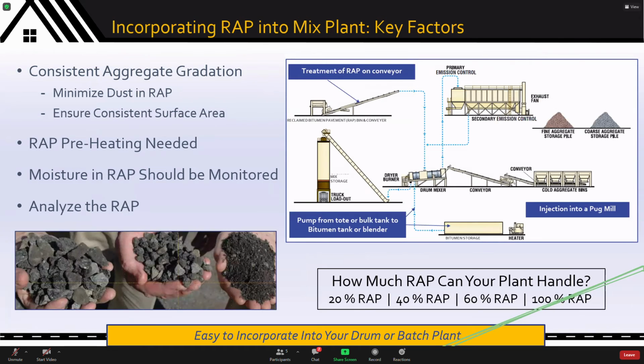So you've done all of this. How do you incorporate high RAP mixes in your plant? Like any input raw material, treat it carefully, measure it well. It is always good practice to try and reduce your RAP piles to different gradation sizes. You can incorporate more and more RAP if you make more and more fractions. This is simply to meet the dry gradation spec requirement that you have to meet. Minimize the dust. Typically, if you want to use high percentages of RAP, you need to have some kind of RAP heating, preheating, and you should control the moisture in your RAP by tarping the pile over.